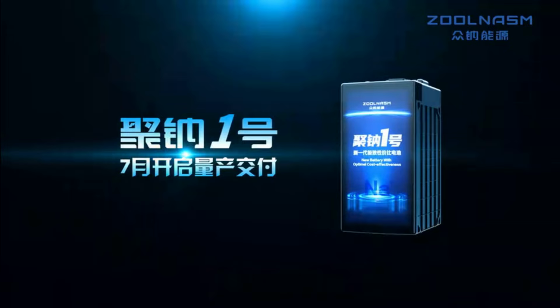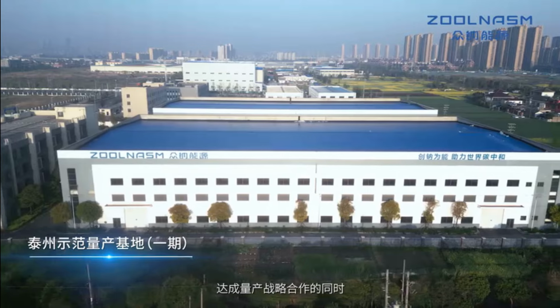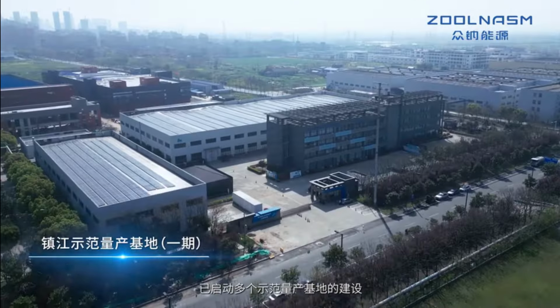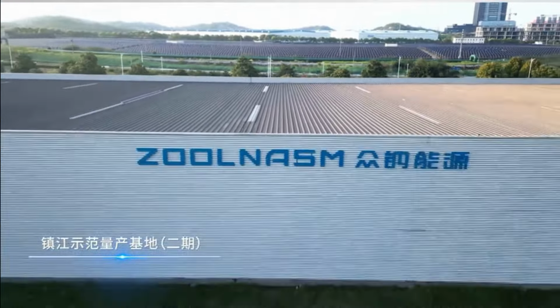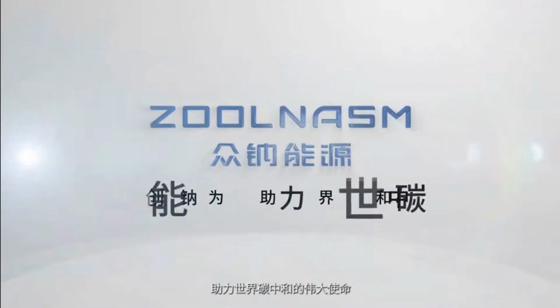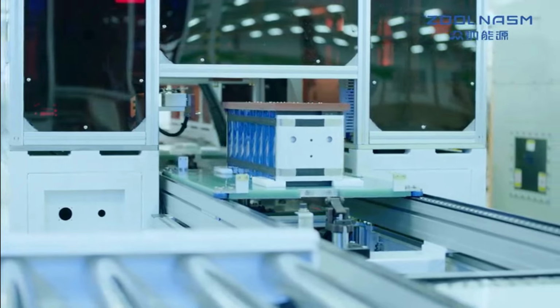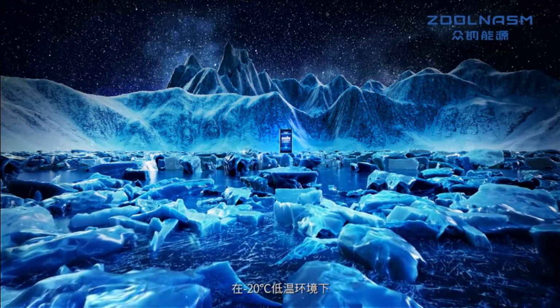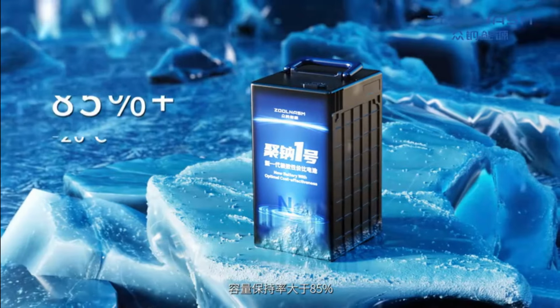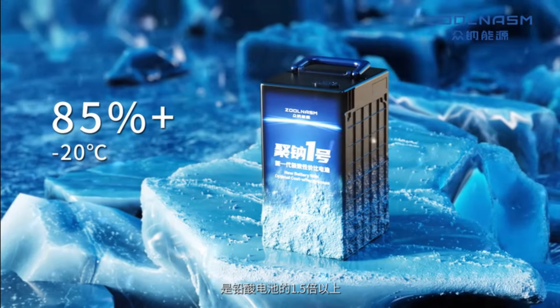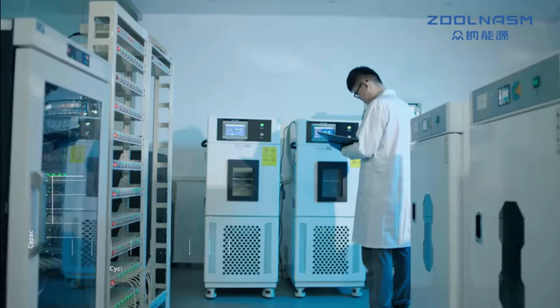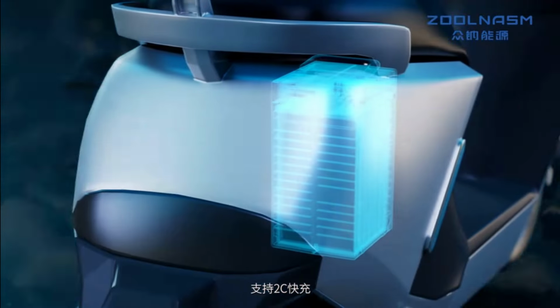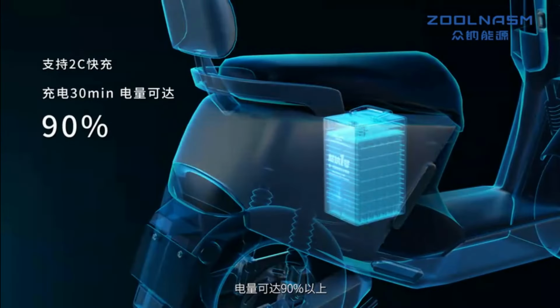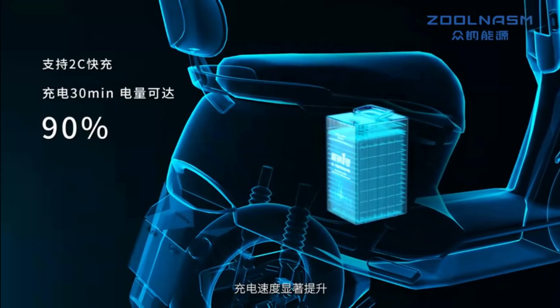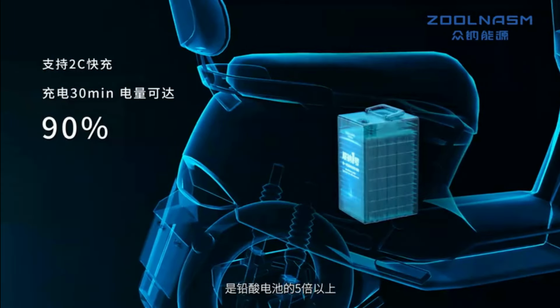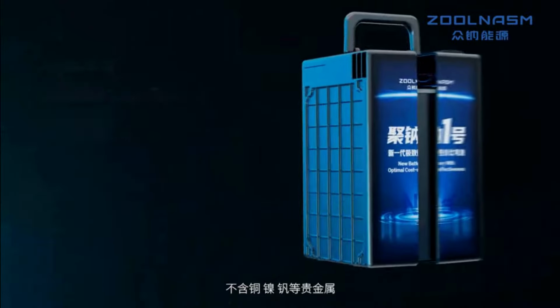The next company we would look at is ZHONGSODIUM. Jiangsu ZHONGSODIUM Energy Technology Company Limited is a well-known sodium-ion battery company in the industry, and it is headquartered in Suzhou, China. The company showed its sodium-ion battery product series in April this year. The cell has several advantages such as long cycle life, good low temperature performance, fast charging speed, high energy density, and good environmental performance. Under the condition of 2C charge and discharge, the cell is able to achieve more than 1,500 cycles at room temperature, and at negative 20 degrees C, it is able to retain more than 85% of its capacity. The cell has an energy density of 122 watt-hours per kilogram.